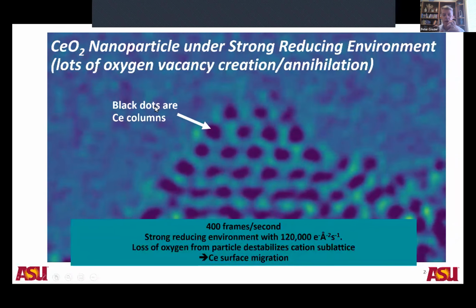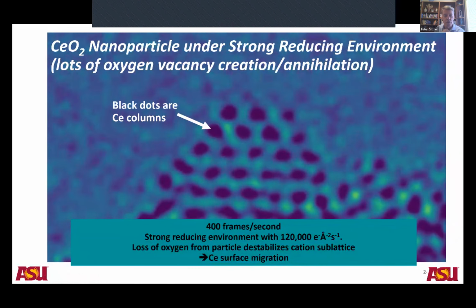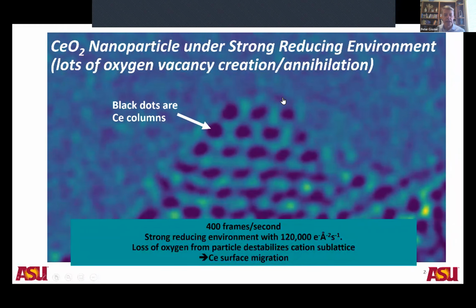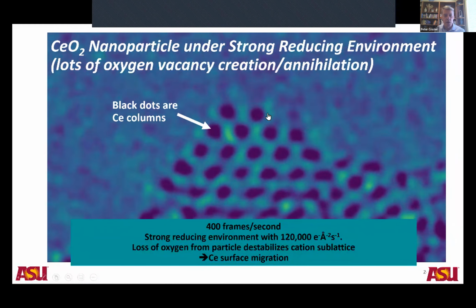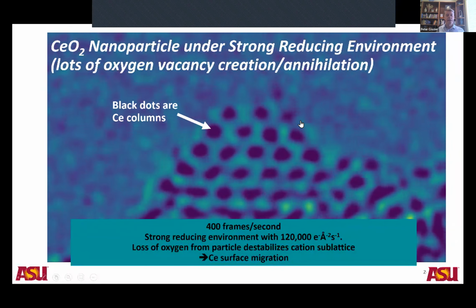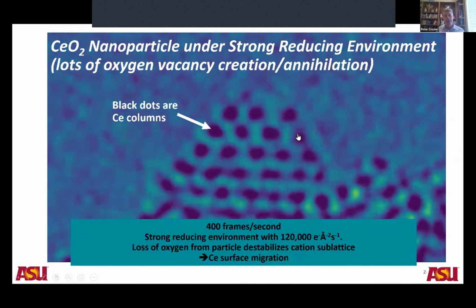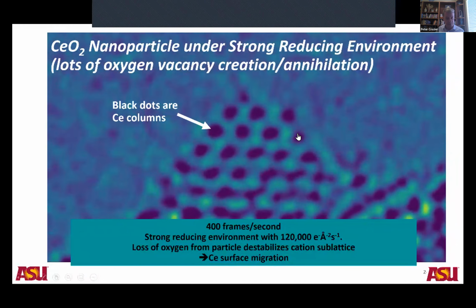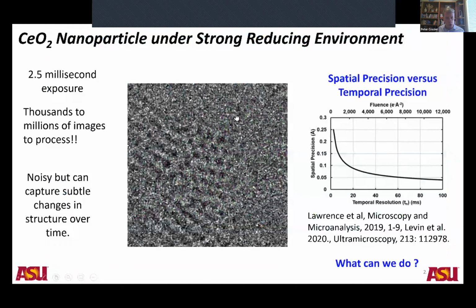And because we're increasing the concentration of oxygen vacancies, we destabilize the cation sublattice. And so you can see a lot of migration of the cations back and forward. And we wanted a system like this so that we could start trying to understand this. Here's what one of those 2.5 millisecond exposure images looks like. So it's pretty bad. It's a little bit similar to the problem in cryomicroscopy.